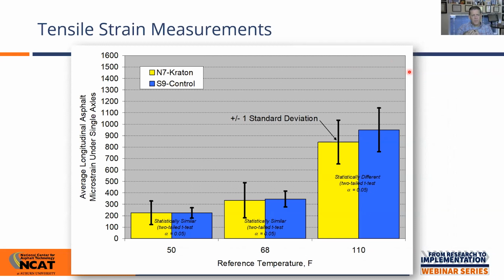To look at the tensile strain measurements, we embedded gauges in these test sections during construction. We made measurements over those 2 years. The vertical scale is the bending strain that we measured under truck traffic, and this is at 3 different reference temperatures. What was really interesting is at the cooler and moderate temperatures, there really was no difference between the 2 sections. And remember that the high polymer section was built 1.2 inches thinner.